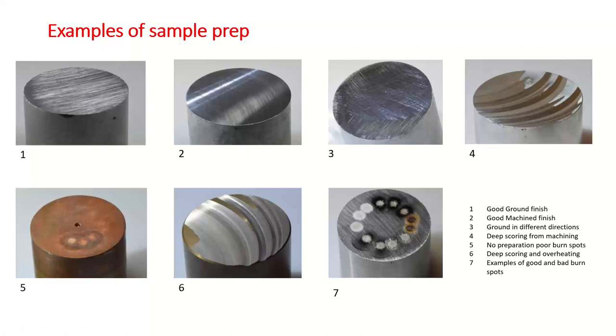You can get it through samples that are not rough enough to create the plasma. That's normally a typical example of where the gas is wrong on a spark system. We use argon gas there to shroud the sample and the spark. If that gas is contaminated, you don't get a burn spot and you get what we tend to call a milk spot. So you get this nice white mark on there, but as you can see, it's not actually eating into the surface of the material, which is what pulls it up into the plasma that we actually measure.